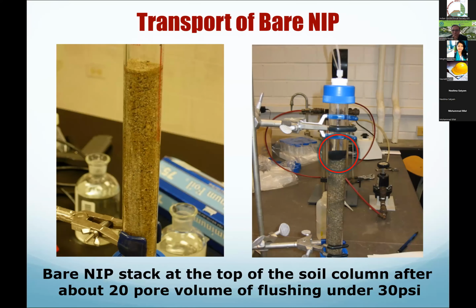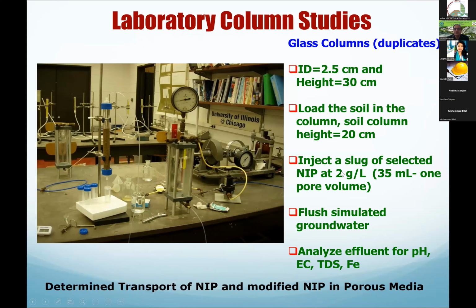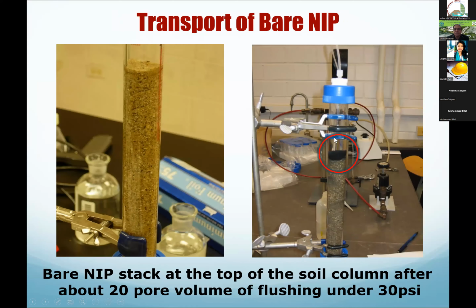So here is the close-up view of the testing. So bare nip, I use the term, basically bare nip is unmodified nano iron particle, right? So here, the soil column that I'm showing you close-up view of, and then we put 1 slug of nano iron particles. Remember what I said here. So we have a 2 grams per liter, 35 milliliter solution of that. We put it on the top. We basically inject from the top down. And then, we see how much of it, and then we flush with the simulated groundwater through that one. So this should be going through it, if it is in the suspension form.